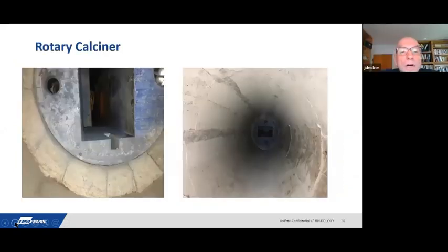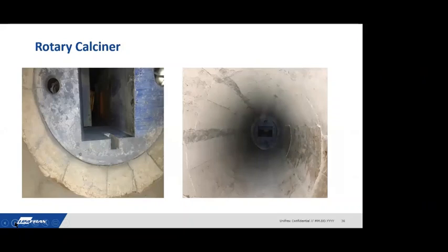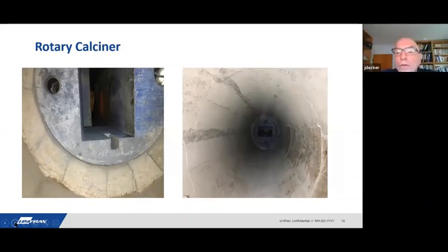This is a rotary furnace, rotary calciner. It's in a petrochemical plant and for waste burning. Now, you might think, well, that drum doesn't really look well installed. I mean, you have really patchwork there. But the guys really did a great job because they worked at very, very high ambient temperatures, above 35 Celsius every day. The material, of course, sets faster at 35 Celsius, but it gave them enough working time to line the furnace and rotate the furnace. So they were actually relatively quick because of that. The furnace now is also in operation for almost 3 years, and we haven't heard anything negative.